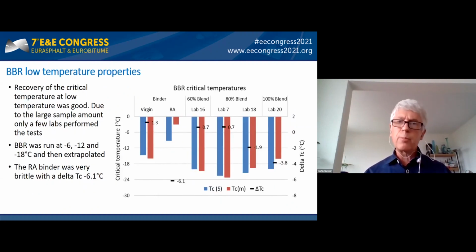So for the low temperature properties, we only have 4 results from 4 labs, but it's covering the whole ratio, 60 to 100%. What you can see is that from the reclaimed asphalt binder, when we make the blend and age it, at the end we have similar results for the blends like the virgin binder here on the left. Even a little bit better if you look, for example, at the critical temperature of the stiffness. We have for the virgin binder around 15, and for the blends, they are all about 20. So it's really nice results which we did obtain for the low temperature properties.